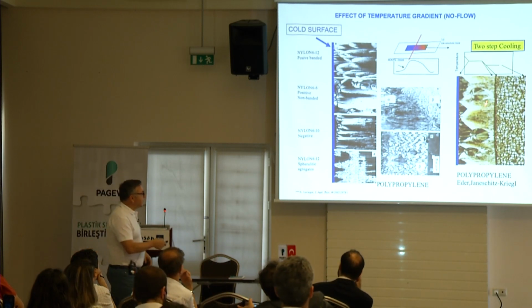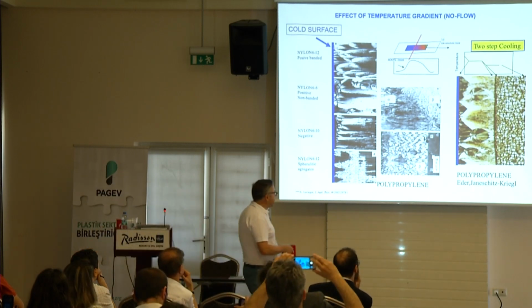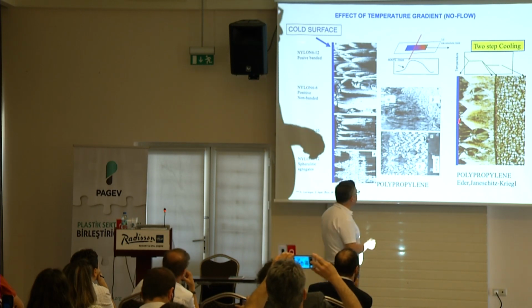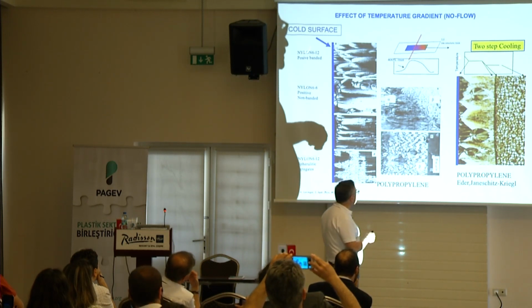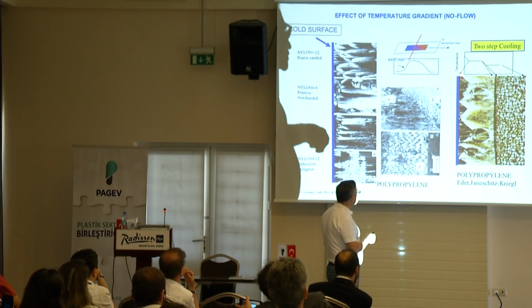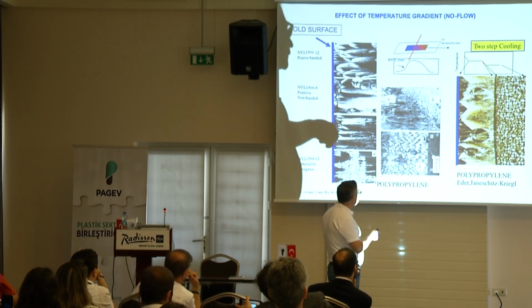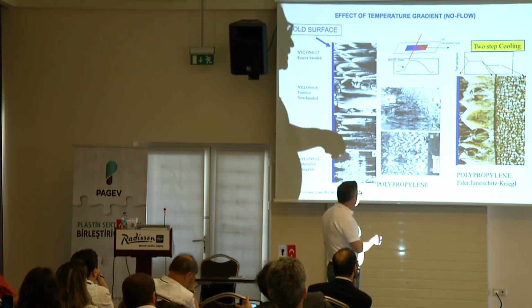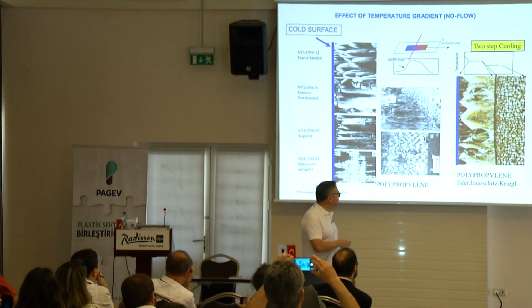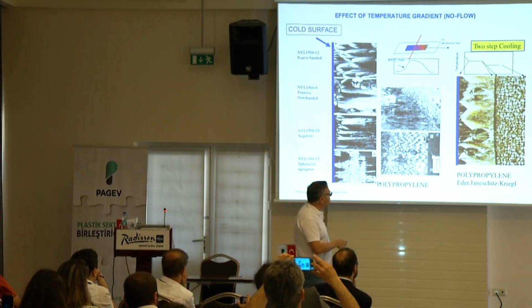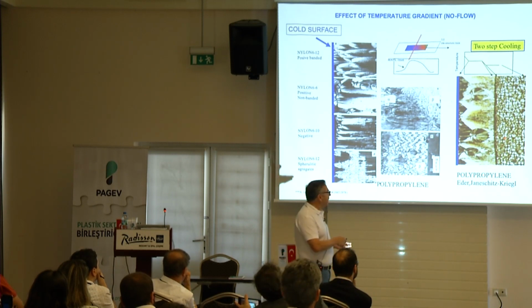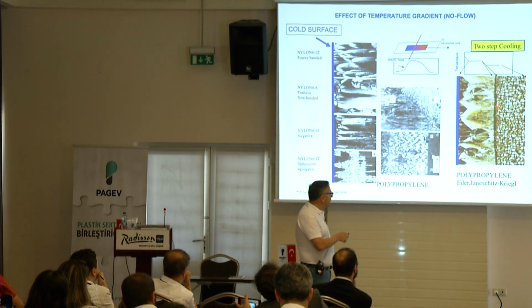Here's an interesting experiment. In this particular one by Kriegel, this is from Austria. He did a two-step process. One is just to quench it into a low temperature, and then he did a second quench to an even lower temperature. You see the difference: in the first case the crystal sizes were relatively big, but in the second case the material has a whole bunch of nuclei, and the morphology changed immediately.